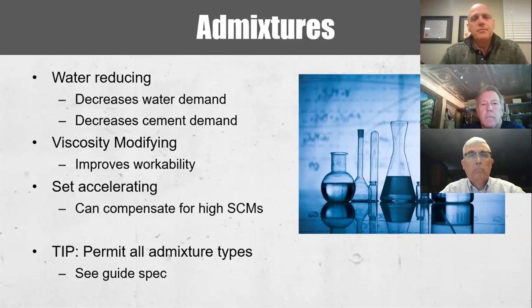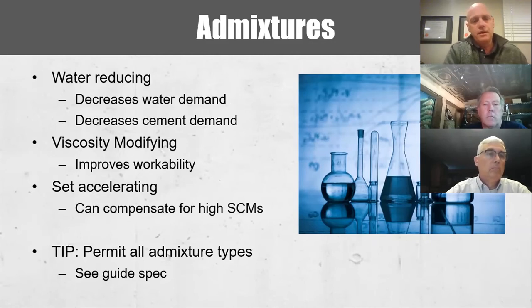The first one I'll talk about is water reducing admixtures. They were invented generally to increase slump of concrete, so you could pump it, place it a lot easier, not require as much vibration on site, and so forth, move it around a lot easier. But the main outcome of that is that it actually decreases water demand, which in effect decreases cement demand. Again, going back to this idea that if you can optimize the cement content in concrete and still get the same strength, then that is a positive and it reduces carbon footprint.